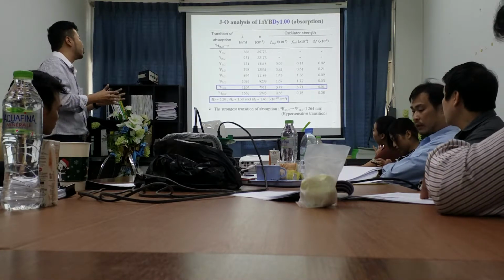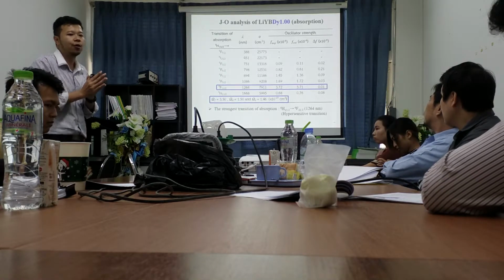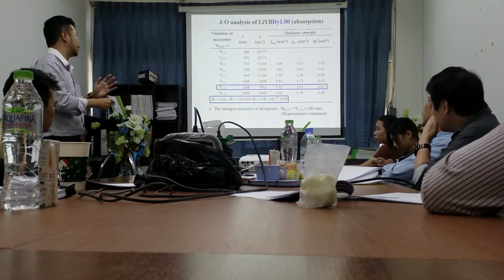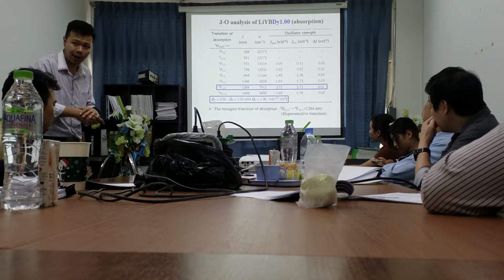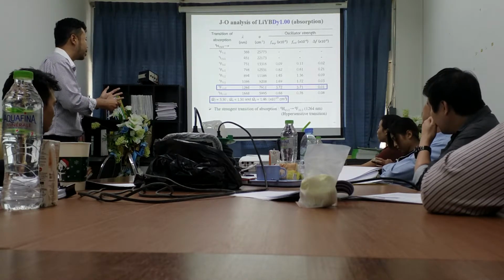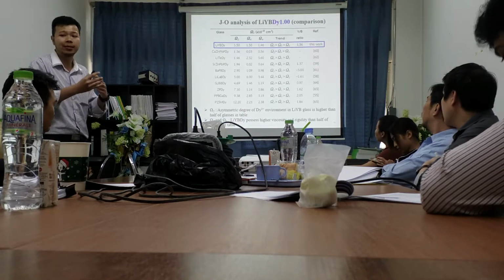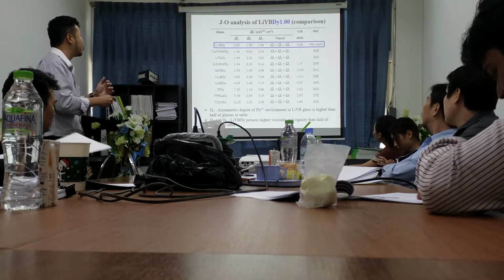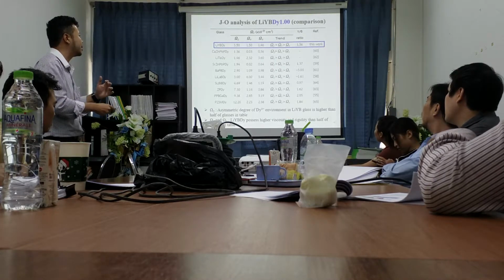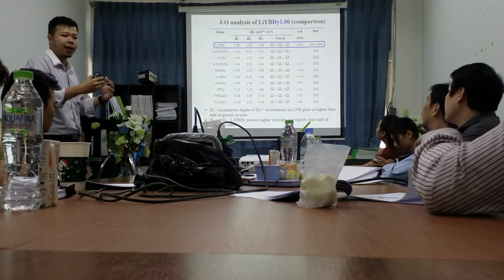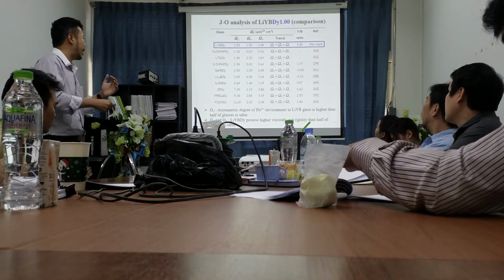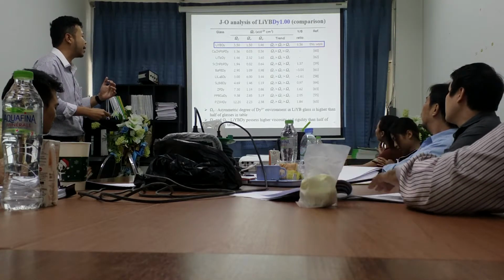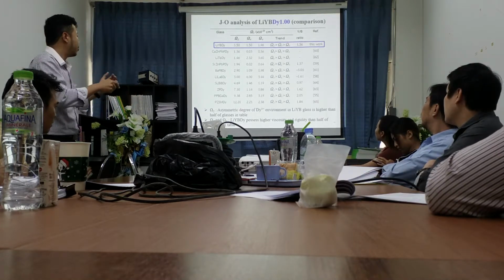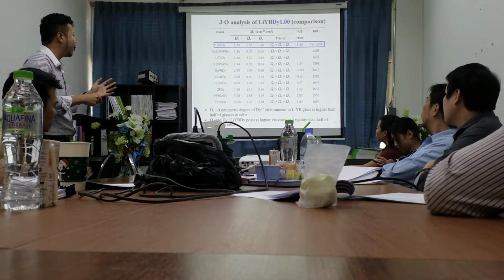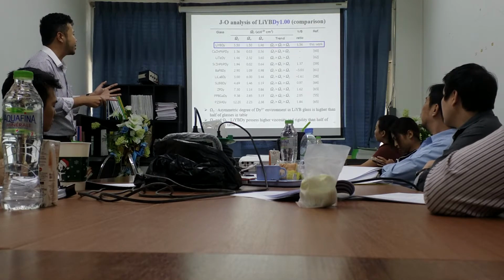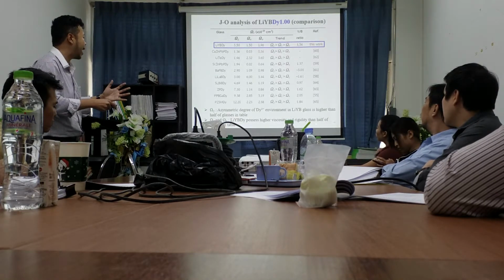Next, I move on to the Judd-Ofelt analysis. The first step of the Judd-Ofelt analysis gives us the omega 2, omega 4, and omega 6 values. Then I compared these values with other glasses from the literature and found that the omega 2 value is higher than half of the glasses in the table. That means the dysprosium ion in my glass has an asymmetry of the environment higher than half of the glasses in the table. For omega 4 and omega 6 also, they are higher than half of the glasses in the table.